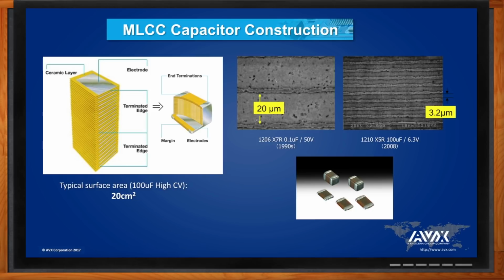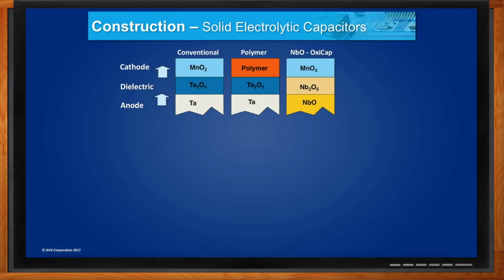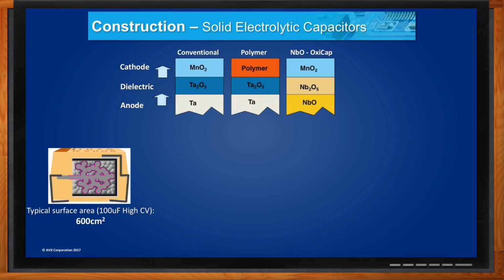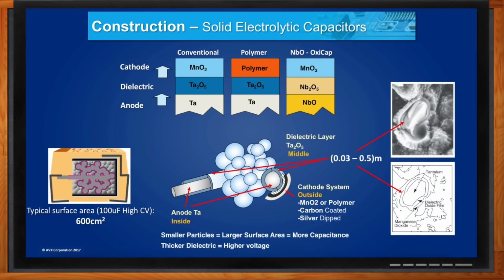Then if we look at solid electrolytics, especially the tantalum niobium family, they start off with a slug with a huge internal surface area in the body, something like 600 square centimeters. And they achieve this by having a powder particle construction where you press a lot of particles together and sinter them, so you have a huge internal surface area like a coral. And then when you grow the dielectric anodically, they grow at something like 20 angstroms per volt that you apply. So some of these 6 volt to 50 volt range, you're talking about 0.03 to 0.5 of a micron. So incredibly thin dielectrics and huge surface area.